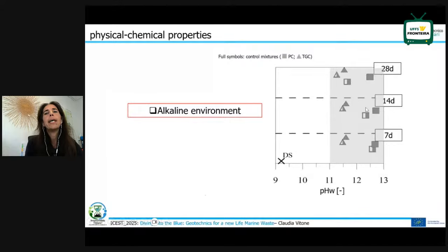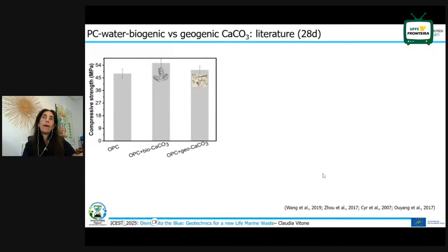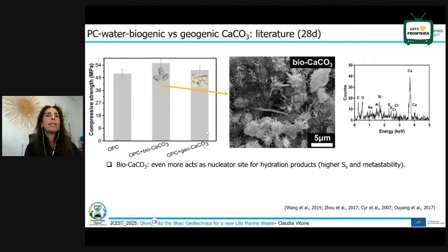And also the pH of the water is suggesting to us that there is an alkaline environment, which is good for the development of pozzolanic reactions. If we look at the literature, where some authors have mixed this shell powder just with cement, so here there are no sediments, and they compared the biogenic calcium carbonate added to ordinary Portland cement to the geogenic one, they also